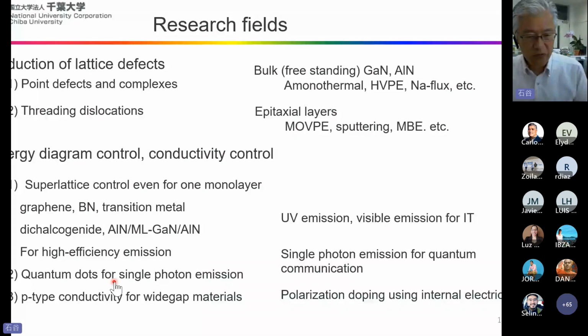And quantum dots for single photon emission are also researched. And for wide band gap materials, p-type conductivity is very difficult. So not only atomic doping, but also utilizing the polarization field in the multilayer structure. This is also utilized, and for aluminum gallium nitride materials, the hole concentration required for the device operation is obtained by this method.